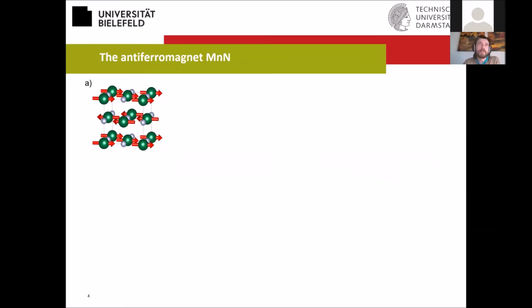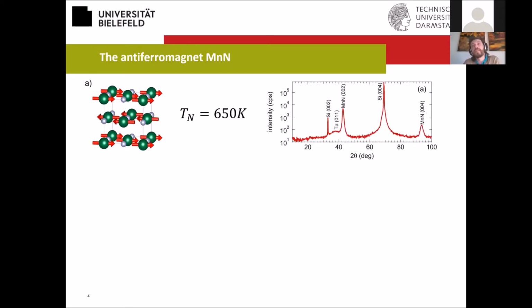insulating antiferromagnets. So our system is manganese nitride, which basically has the sodium chloride structure with a little bit of tetragonal distortion. It has a high Néel temperature, so you can do room temperature experiments with this. We grow our thin films basically on a tantalum seed layer on oxidized silicon substrates. So these are polycrystalline films, which are, however, nicely oriented with the manganese nitride growing along its 001 direction perpendicular to the film surface.